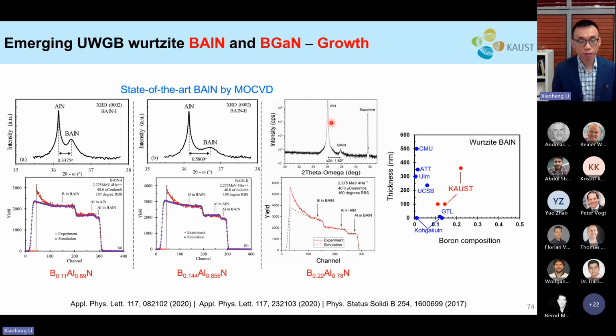Okay, so without getting into too many details, we have demonstrated state-of-the-art BAlN by MOCVD. So we realized the boron composition from about 11%, as you can see here, to about 14%. And then the latest is about 22%, right? But of course, as you can see, when we have higher boron composition, the quality of the BAlN layer starts to decrease, okay? But nevertheless, now we have materials up to about 22% or so for different research for BAlN. The aluminum nitride epitaxy on silicon earlier was actually developed based on this study as well.